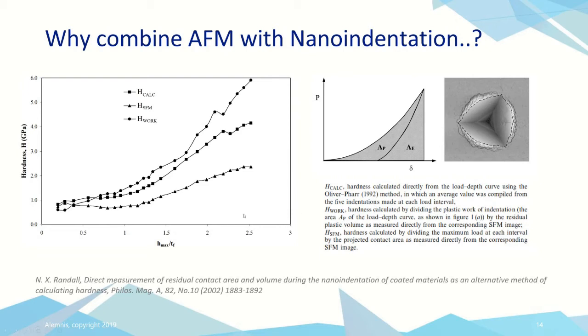And so very clearly here, if we plot those three methods on the same axes, this x-axis is the ratio of indentation depth to film thickness. So 1 is basically the interface between coating and substrate. Anything deeper than 1, we're into the substrate. And what we see is that while we're in the coating, where we know there's not much pileup, the three methods are fairly similar. But as we go into the substrate and we start to get much more pileup, we see that the methods start to give different results.